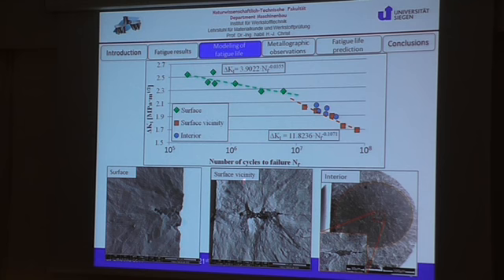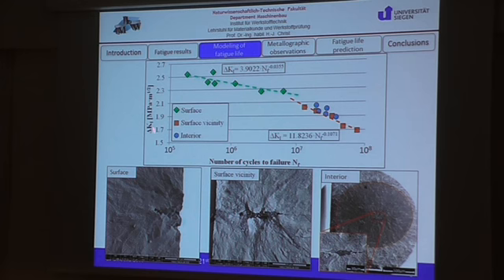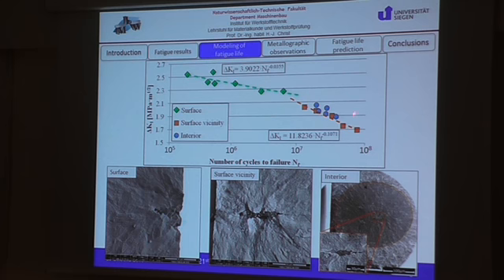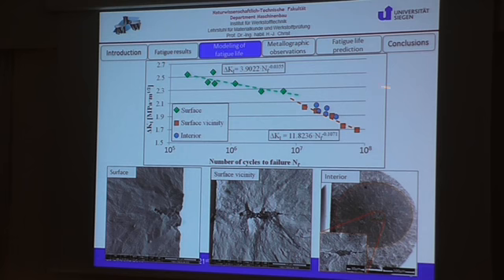The first group of data corresponds to inclusions on the specimen surface and in the vicinity of the specimen surface. The other group — the blue points — are specimens with crack initiation in the specimen interior, deep below the specimen surface. These show more pronounced scattering, and all points lie to the right of the defined correlation between delta K and number of cycles to failure for internal inclusions, presumably due to an extended crack propagation period.